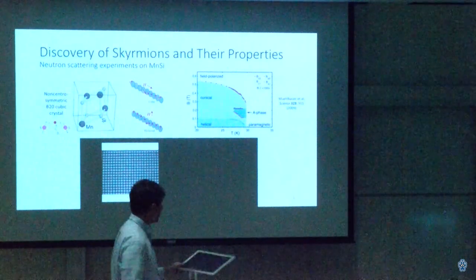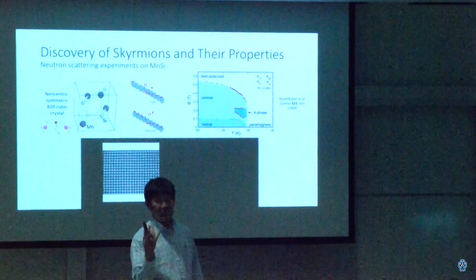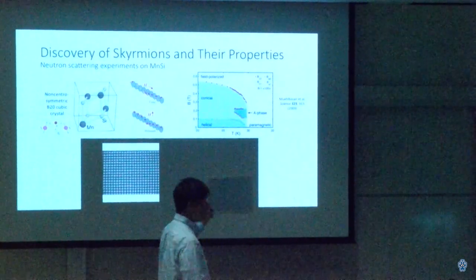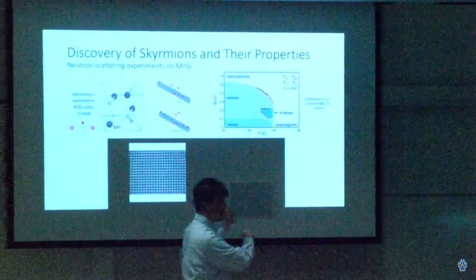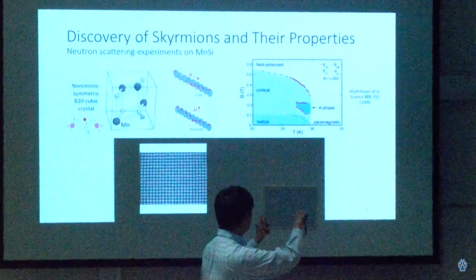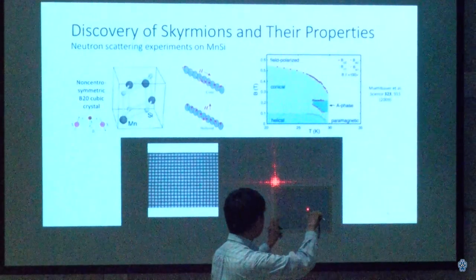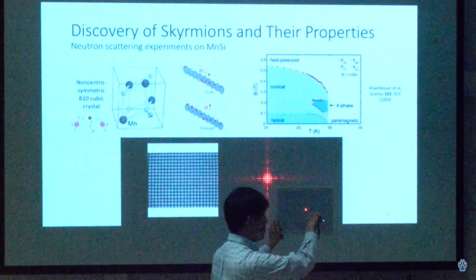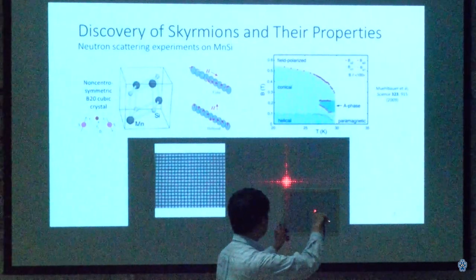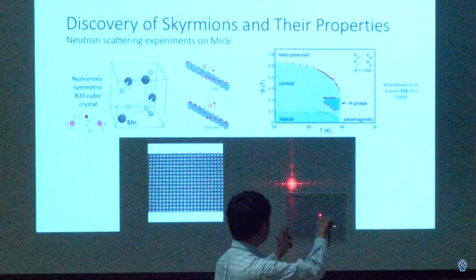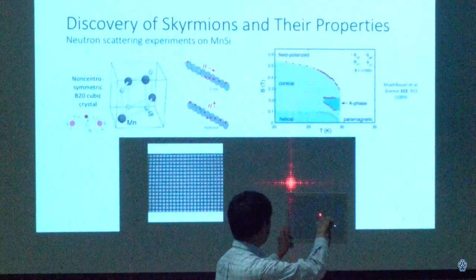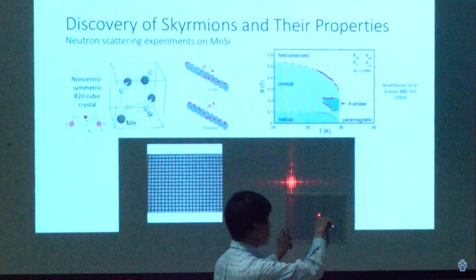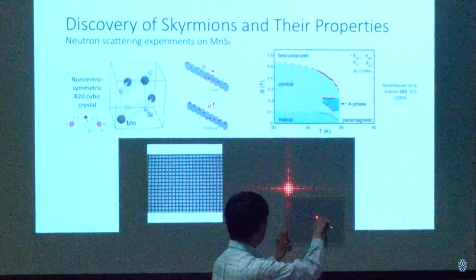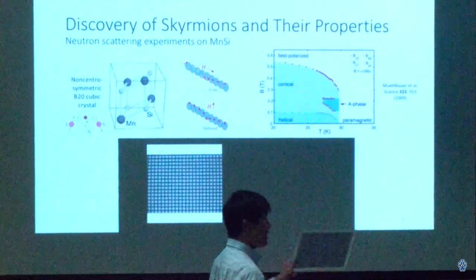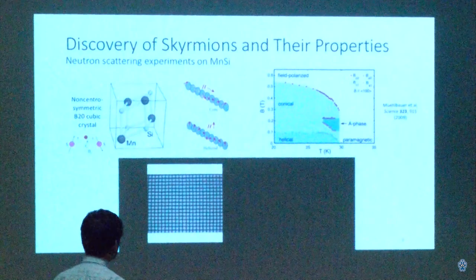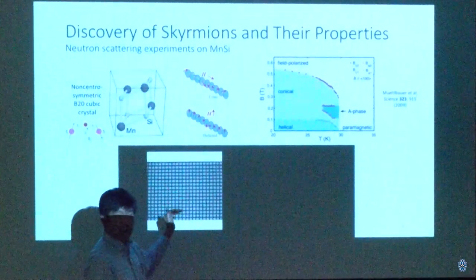What Mühlbauer and company do is essentially send a beam of neutrons. This is a laser, but pretend it's a neutron source. Through their material, not a net, but a crystal of manganese silicide. And what they got was a diffraction pattern, just like I'm getting with the laser and this mesh. You can see that this square mesh produces a pattern of points that are distributed over a square lattice. Knowing that the points are over a square lattice may not tell you that you have a square mesh, but it does tell you that things are arranged in a square fashion.